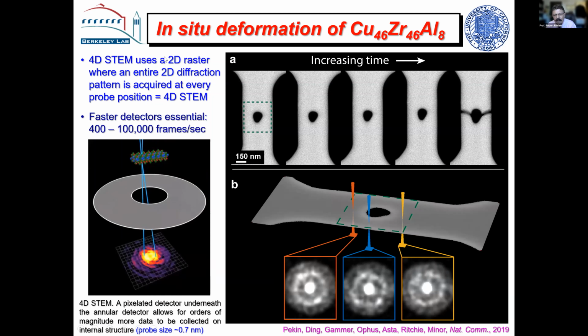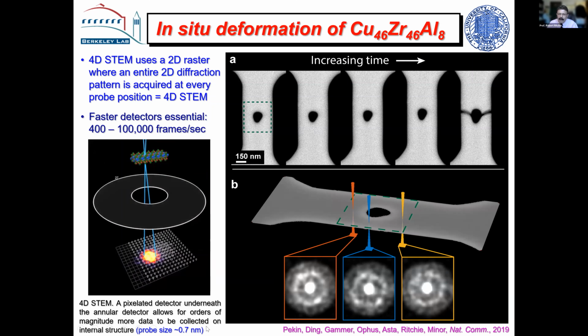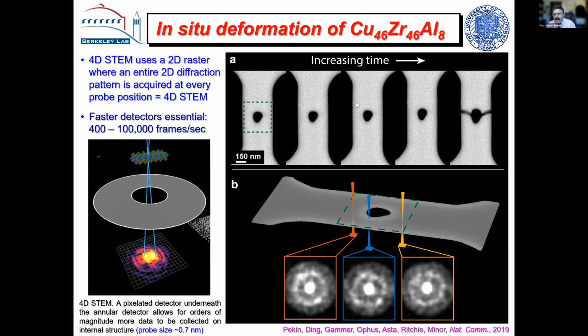He has this 4D STEM technique where we can look at little tiny regions of atoms. They're of the order of about a half a nanometer, and we can look at columns of atoms and we can see the structure. But the key is we can move very quickly throughout a whole lattice because we have very fast detectors that can see these things. So we had a little sample with a hole in it here, and we pulled it in the microscope, and we tried to see the regions of where there was less icosahedral symmetry, where there were more GUMs, and whether they were the regions where the shear bands formed.